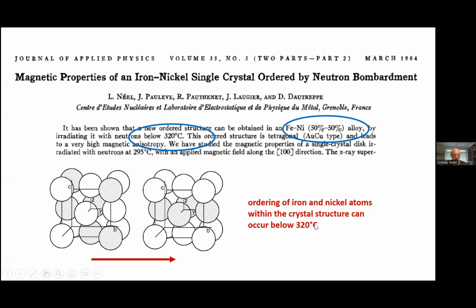But the point about this ordering only below 320 is that the atoms are very slow moving below that temperature, and that's why the neutron irradiation is needed. If you didn't have the neutron irradiation, it's reckoned that this ordering would take up to about 10,000 years.